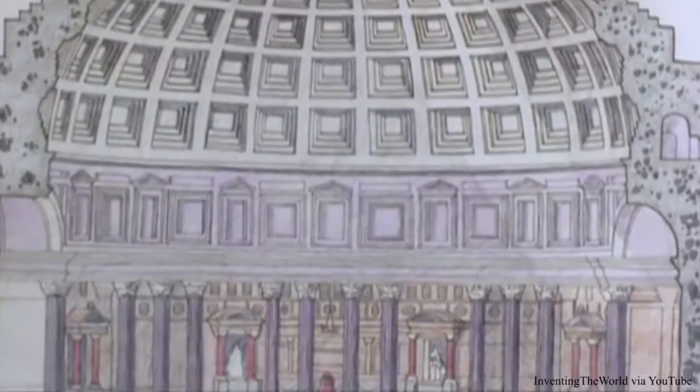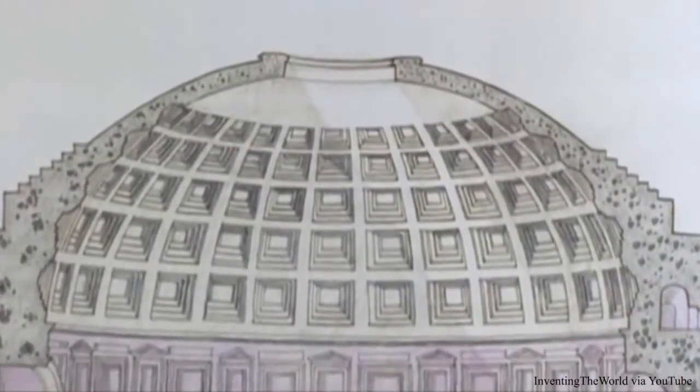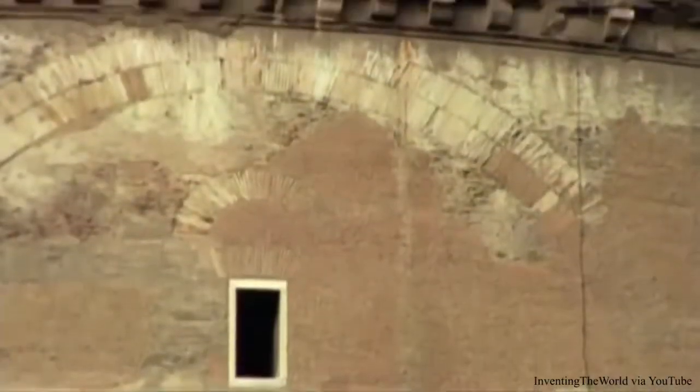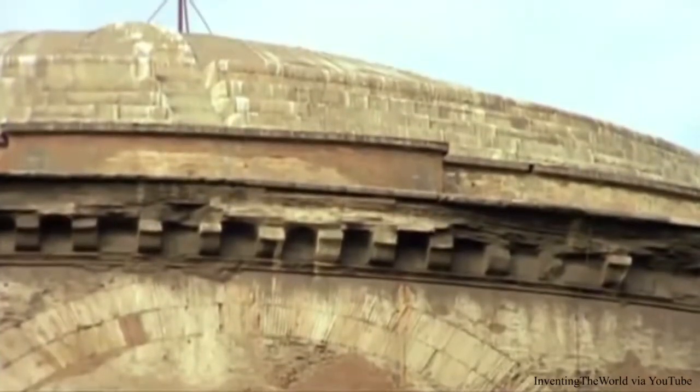The critical issue here is that it's this combination of the lime with the alumina and the silica that gives us these stable minerals. Lime on its own is not stable. The Romans, when they initially did their building, of course only used lime mortars. When they discovered that by mixing the lime with volcanic ash, they could make a much more durable material — one that would also sit under water — that was the beginning of what we call hydraulic cements.